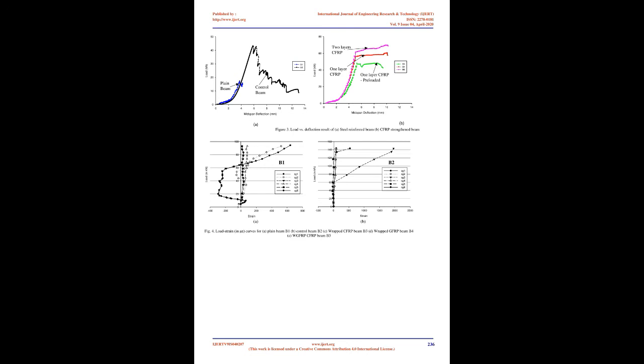Beam B4: the concrete beam strengthened with 1 layer of CFRP fabric failed due to yielding of steel followed by rupture of fabric and crushing of concrete at midspan. After failure, flexural cracks are observed in the beam. Shear cracks are not observed.